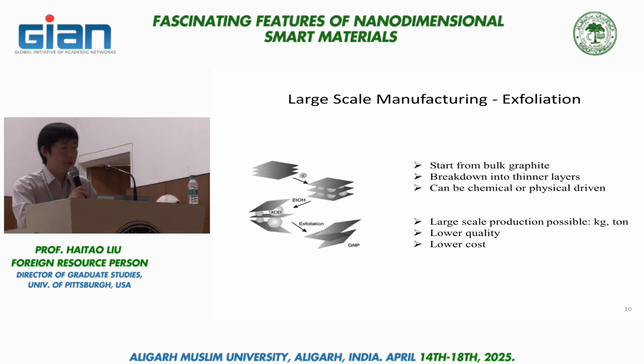Okay, so to give you 3 different examples of exfoliation. On the top is acid intercalation. In this case, you have graphite. You treat it with strong oxidizing acid. Acidic molecules come into the layers, and then you just heat it to high temperature. There will be thermal decomposition of those intercalated molecules that expands the graphite lattice. And shown here are the scanning electron microscopy images of this expanded graphite structure. You see a lot of sheet-like structure, but it's difficult to see whether it's single layer or not.